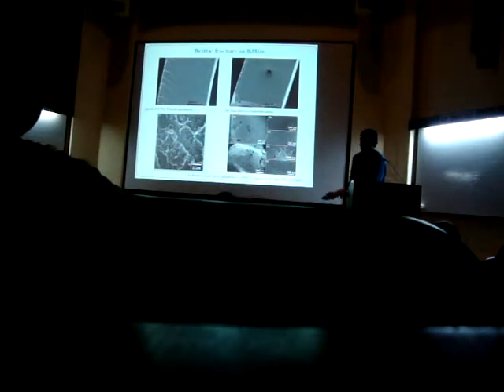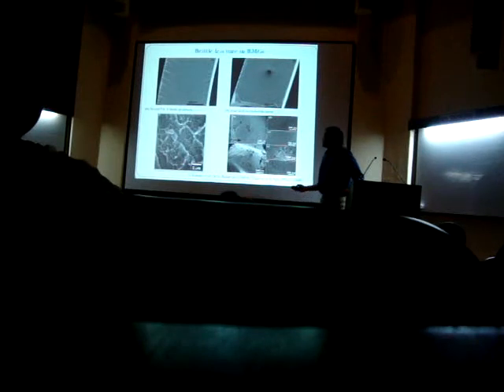Okay, so this is the conclusion of the topic: this is the first time that we have not used elastic parameters but rather plastic parameters to describe what is happening in a metallic glass that leads to better shear band formation, which ultimately leads to better fracture toughness. Now we move on to brittle fracture, where